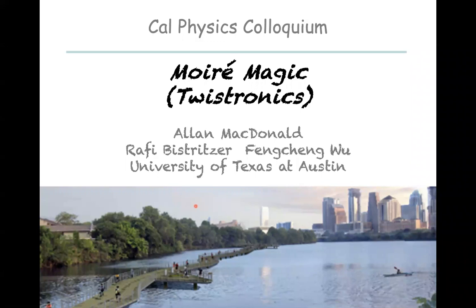In particular, magic angle twisted bilayer graphene has, on top of strong correlations, topological properties that give you the quantum anomalous Hall effect, seen across the bay at Stanford for the first time by Goldhaber-Gordon's group. At the same time as it has that topology as a unique new feature, it seems to have these large Fermi surface reconstructions, changing Fermi surfaces by large areas, and seemingly critical behavior associated with these changes of Fermi surface area that have been hard to understand in cuprates and are hard to understand here. But hopefully we'll be able to do some new types of experiments which will give us a new angle on trying to understand what's going on. So thank you very much.